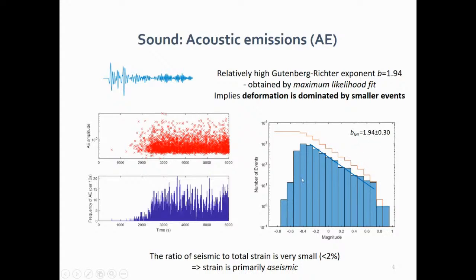Another thing we can do is count up the amount of deformation from the inferred seismic moment and compare that with the total strain that you would expect from the bulk deformation. And we get a very small ratio of the seismic moment to what you'd expect given the strain that you observe on the sample. So it's less than 2%, depending on where you pick this threshold or how far you extrapolate it back. And that means that the strain is primarily aseismic. So all these stable shear, the rotation, they seem to be dominating the actual strain in this case. So the acoustic emissions are only really recording a tiny proportion of what's going on in this case.